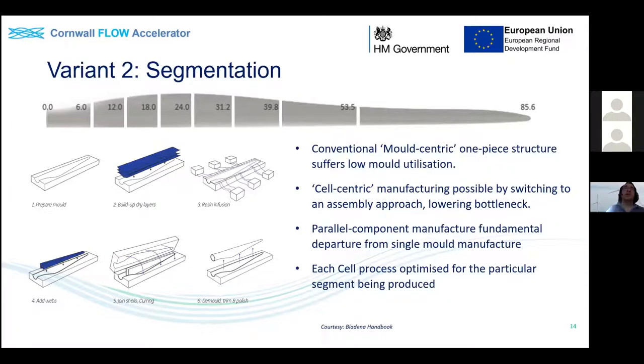So instead, by segmentation, where we're simultaneously manufacturing a number of different blade segments, which one or two manufacturers currently do in terms of splitting blades into two, we propose a very cell-centric manufacturing process where, depending on the geometry and the mass of material that needs to be placed in the mold, there are other manufacturing processes which are better suited to those smaller segments. So it really allows us to optimize the cost and minimize the time in manufacture to achieve some good outcomes.